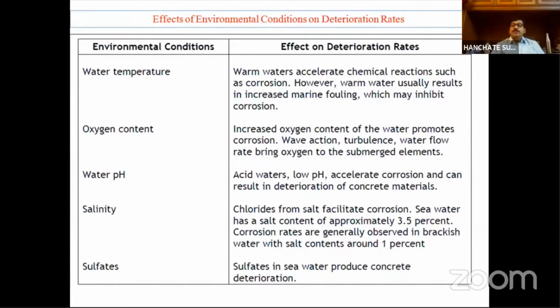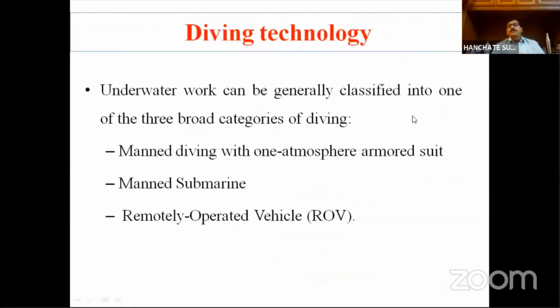Seawater has about 3.5% salt content, and corrosion rates are generally observed to be very high when the salt content is around 1%. So if the salt content is about 3.5%, you can imagine how much corrosion will take place under seawater. Similarly, sulfates are another very important phenomenon which will assist the deterioration under water.